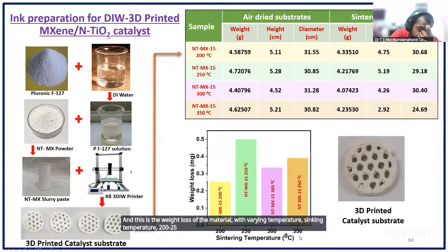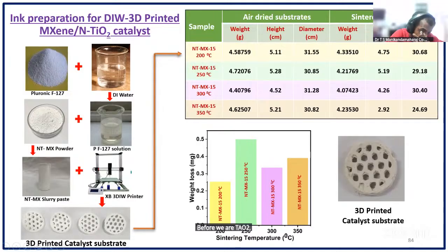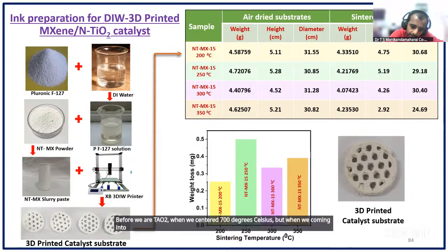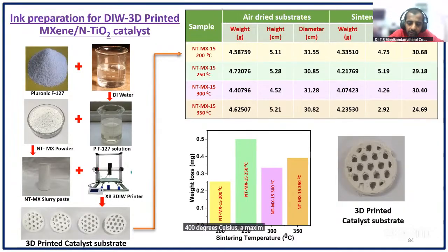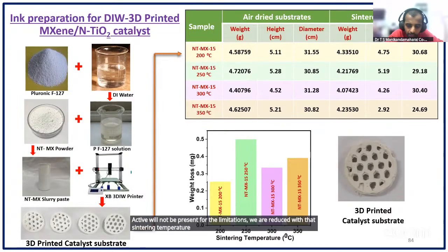Before, with TiO2, we sintered at 700 degrees Celsius. But here, for the same TiO2, we reduced the temperature because we are adding MXene. The MXene property is that if we go above 400 degrees Celsius, the MXene activity will not be present. Because of that limitation, we reduced the sintering temperature to below 400 with the MXene composition.